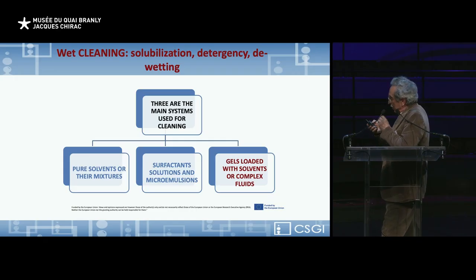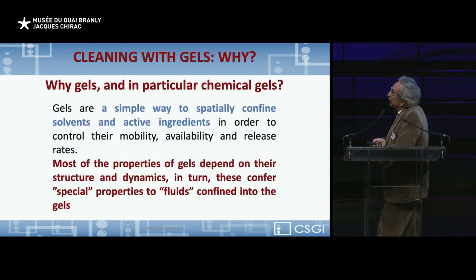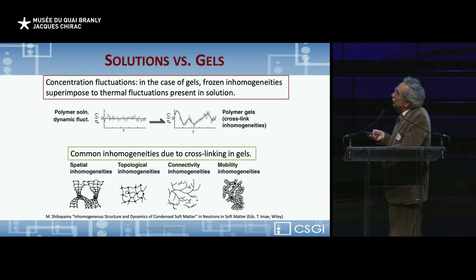If you really want to control the cleaning process, you have to use gels. Why do you need to use gels? We use mostly only chemical gels, or gels that behave in a chemical way. Why? Because we need to control the three-dimensional structure, the 3D structure of this gel, and the dynamics of the gel, because when you load the gel with the fluids, they change their behavior according to the gel. So they interact with the gel, and you have to control the topology you have in the gel. And if you control the topology, you control the dynamics in the gel.